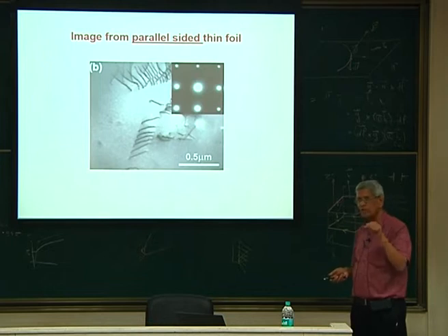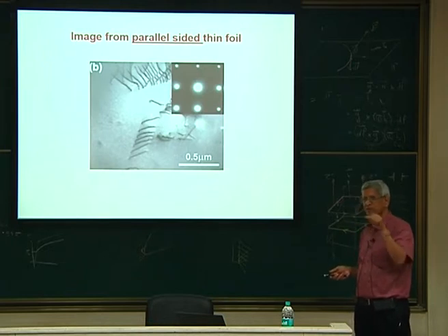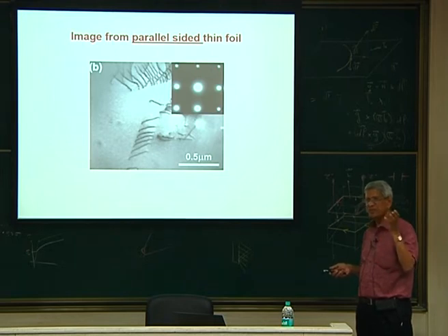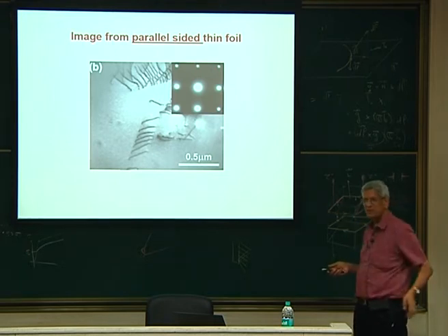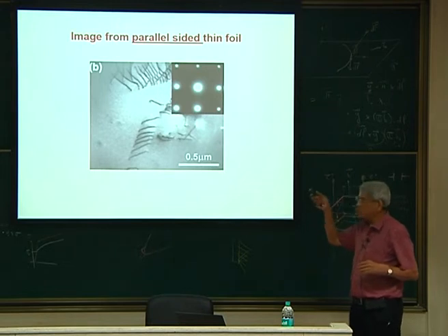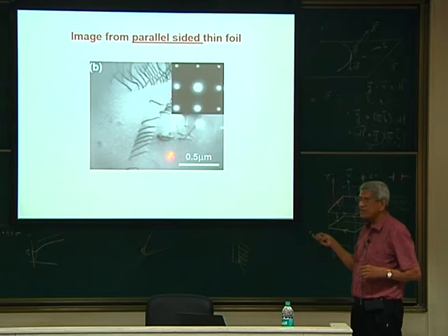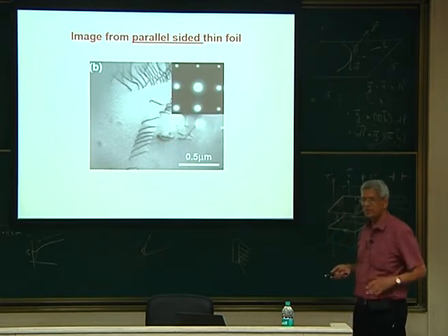But you know that for the dislocation, if you look at it, most of the disturbances are around a small region of 3 times the Burgers vector or 5 times the Burgers vector. So that is the region from which this type of contrast is coming. So essentially, when these sort of contrast variations are there, that is an indication that some defect is present in the material.